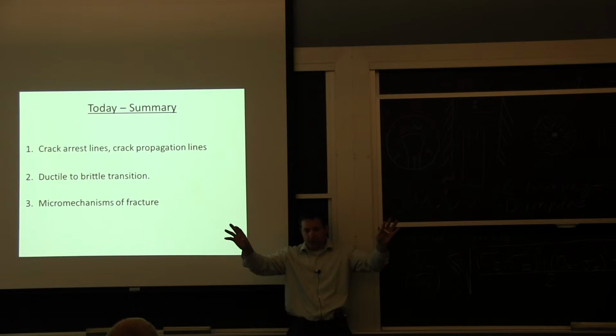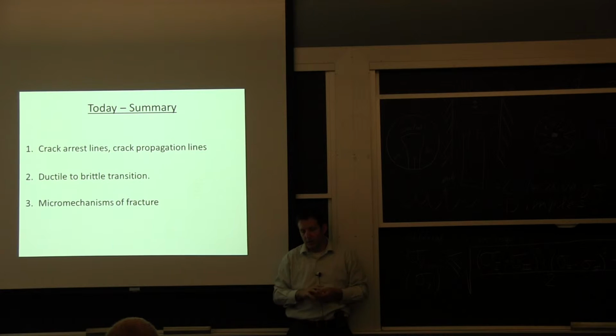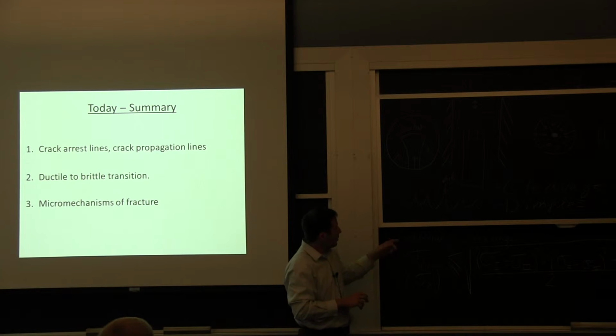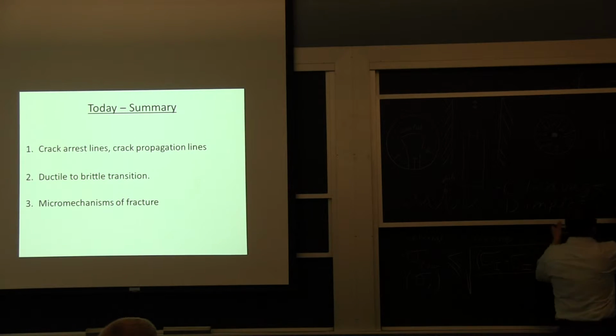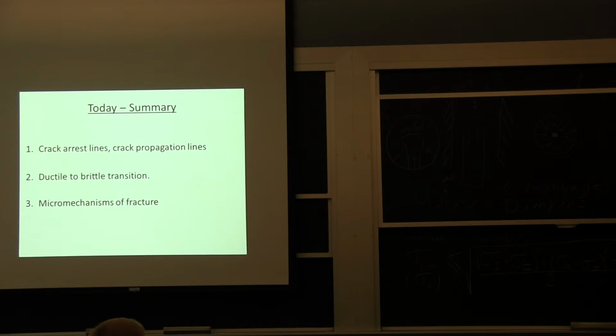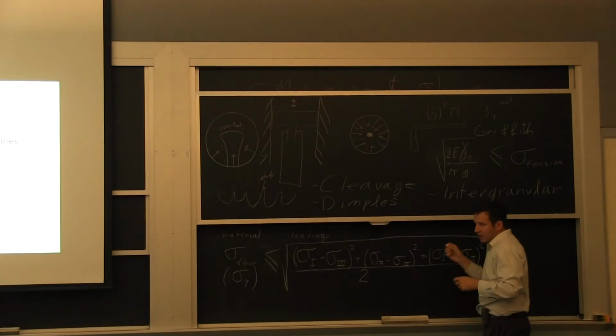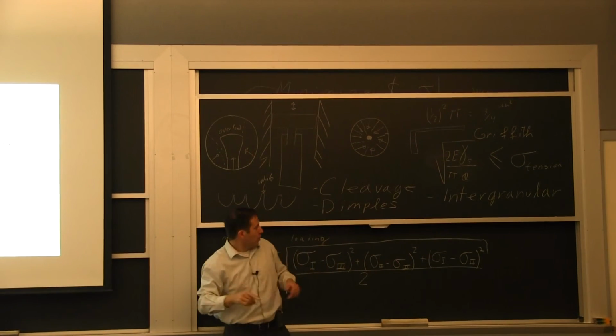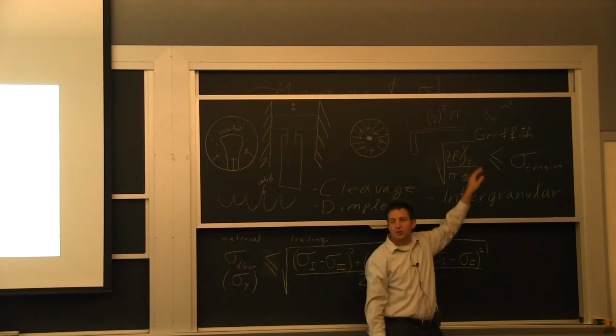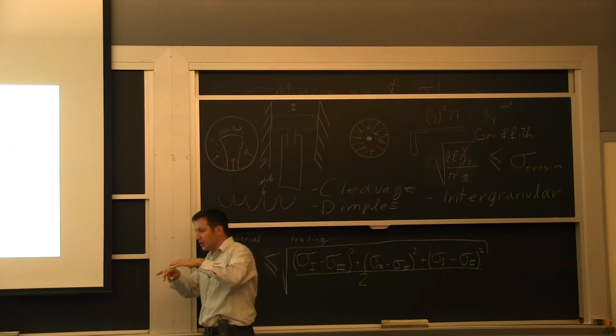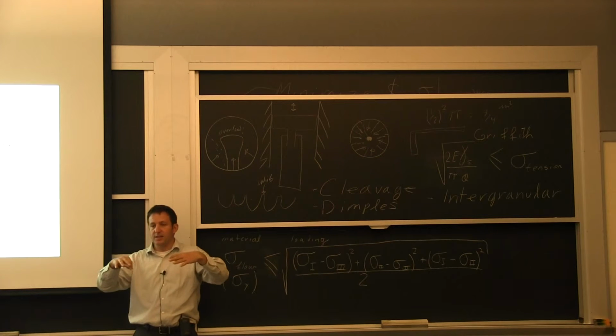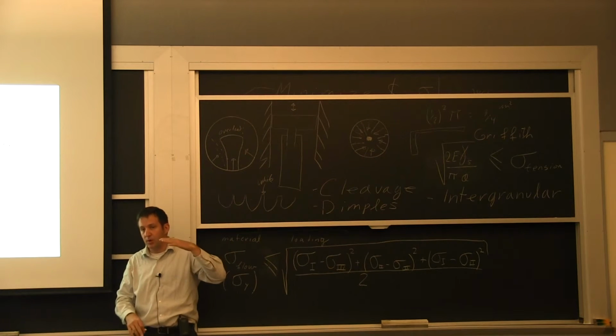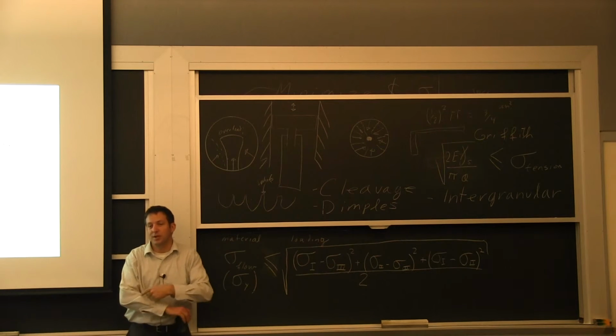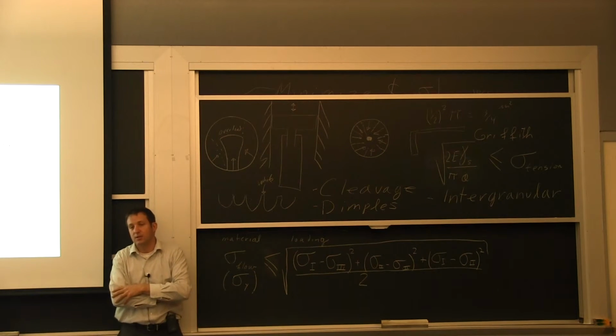It's diverging in a ductile behavior. The one exception is when you have a brittle behavior at very low temperature, and we talked about the reasons for those differences. We have cleavage, dimples, and the other one that I've talked about today is intergranular fracture. If it's due to hydrogen embrittlement, if you have too much hydrogen in your material, it's essentially working on the capacity side here, how much energy it takes to form new surfaces. The hydrogen just very rapidly gets localized in the high stress regions, and it's helping the separation. So it's one of those few situations where you're actually affecting how easy it is to crack.